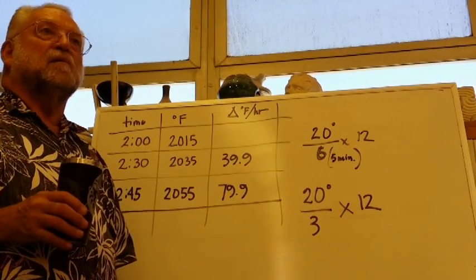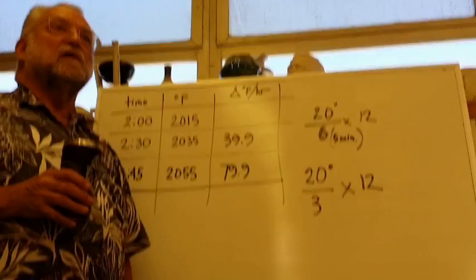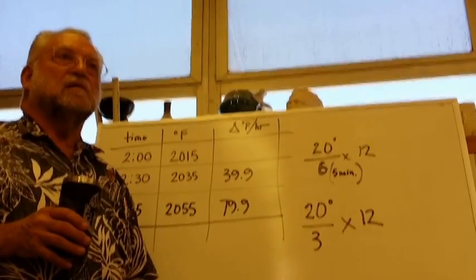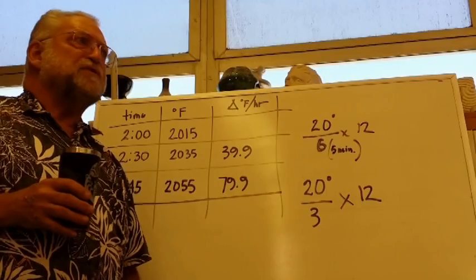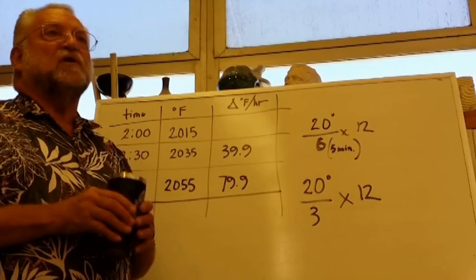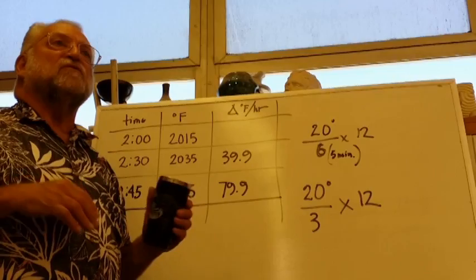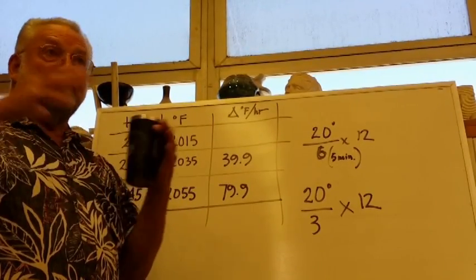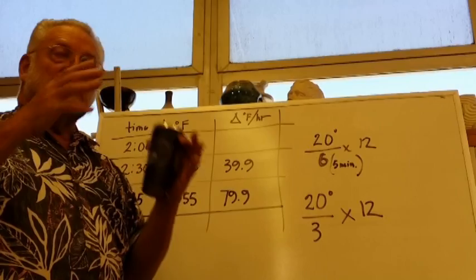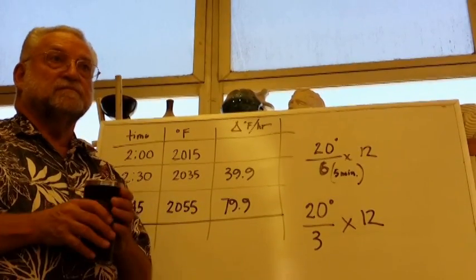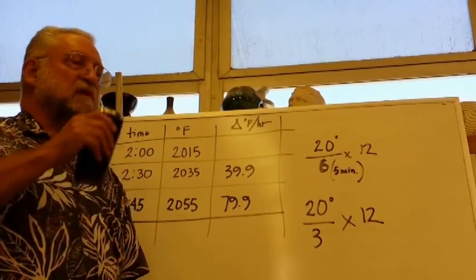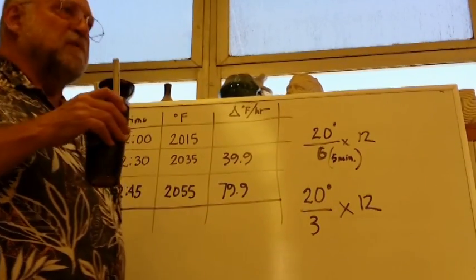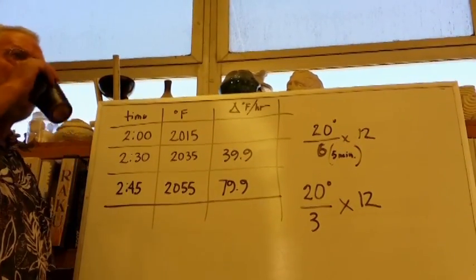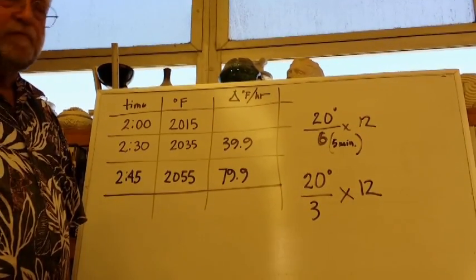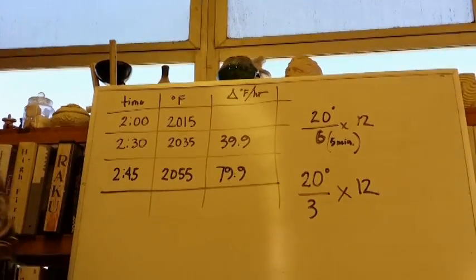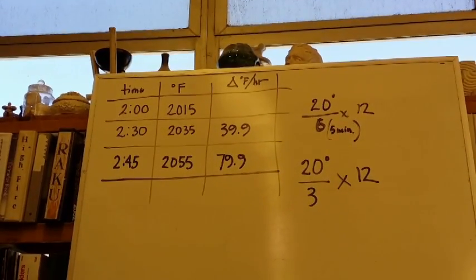So anything over 100 degrees of climb per hour can risk some problems, cracking. Most of what we do in the high fire process requires time for glazes to melt, off gas, smooth over, and give us a nice clean surface. And you found that going 100 degrees per hour gets you that? That would be a maximum. That'd be a quick fire.